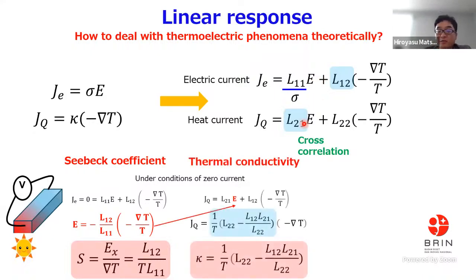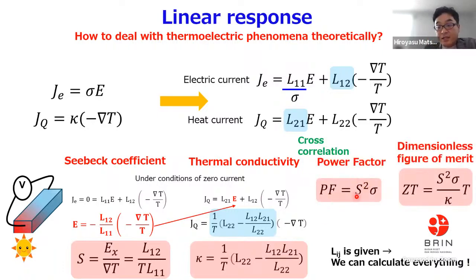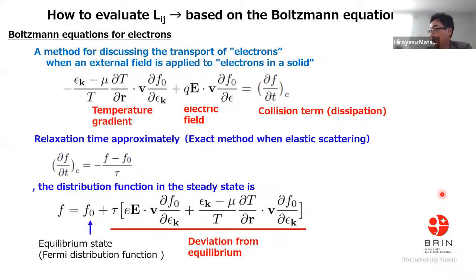And for the thermal conductivity, we can also get these equations. This equation also has L11, L12, L21, and L22, each being this coefficient. And the power factor is like this, and ZT, which I discussed on the previous slide, is defined by this equation. So the important point is that if we know L11, L12, L21, and L22, we can calculate the Seebeck coefficient, kappa, the power factor, and ZT. Therefore, we need Lij.